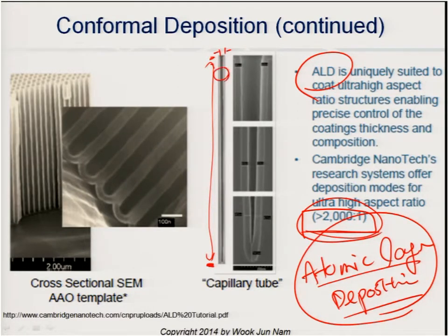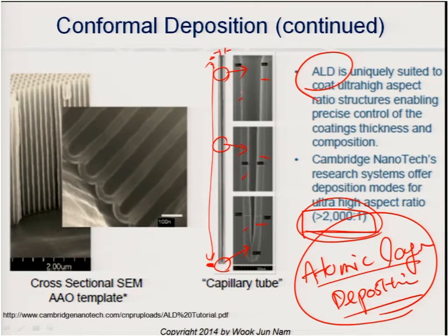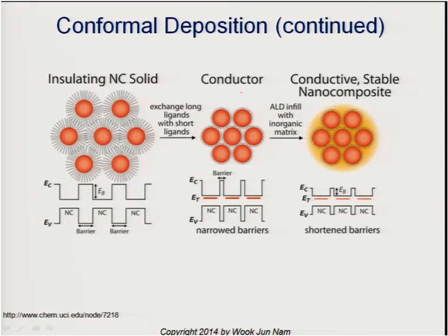So when people cut here, here, and here, they just see that measurement of the lateral film thickness, and atomic layer deposition offers almost perfect step coverage. This atomic layer deposition technique is used for many applications in nano device fabrication because of this good advantage.